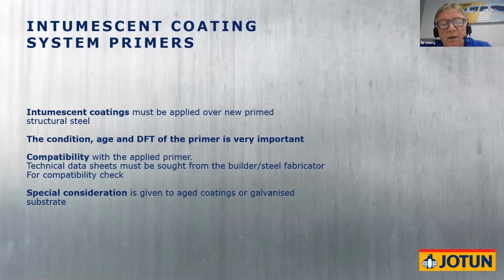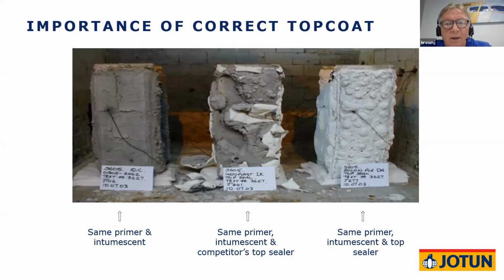On the primer systems, we accept that steel is sometimes fabricated overseas, so we just say make sure it's a good quality epoxy primer. But on the top coat, it's important for specifiers out there that you specify the same top coat manufacturer as the intumescent. On the left-hand side, you can see a piece of steel which is the same primer and intumescent. The right-hand side is the same primer and intumescent supplier, and it's a nice even char. If we look in the middle, you can see areas where the paint has not swelled, it's not expanded. And this is because it's not worked with that particular top coat. The top coat's prevented it. So make sure if you specify, you always do specify the same manufacturer for top coat and intumescent.